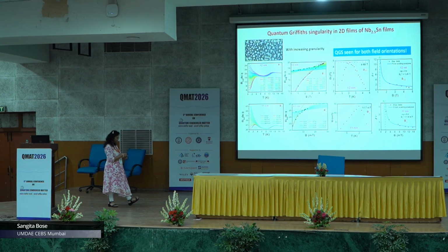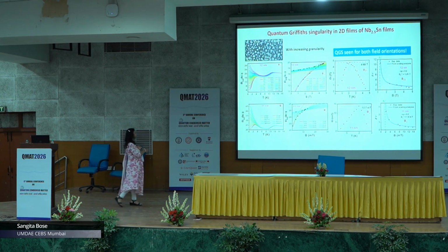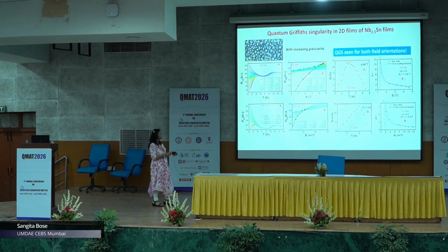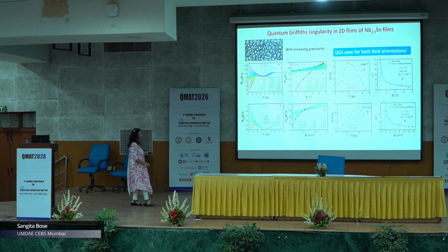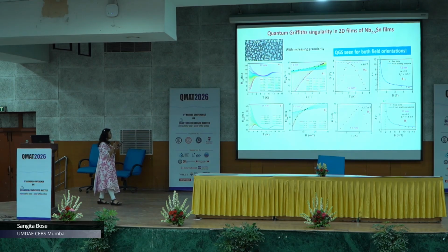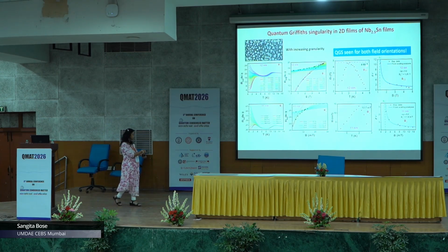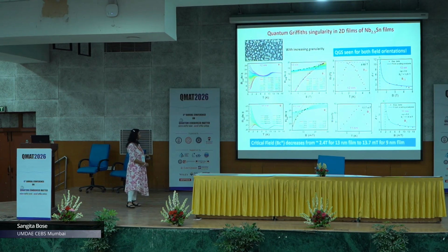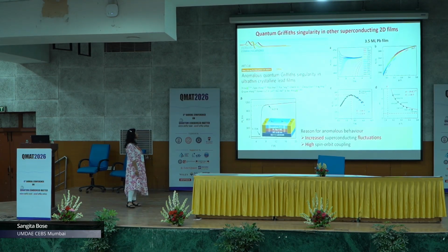Of course, this is for the parallel orientation. For the previous one, for the perpendicular orientation, we got around 2.4 Tesla. Here, this has reduced to around 13.7 millitesla. So, applying a very little magnetic field is bringing us closer to the quantum critical point. So, this is what we see.